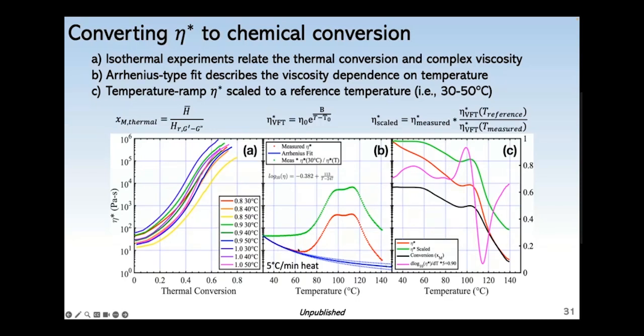And the raw viscosity is red. So afterwards, I scale the complex viscosity, accounting for that temperature change, or how much I would expect the viscosity to change with temperature. And that green line is showing how much it's been scaled to account for that temperature dependence. And then in the last plot, I'm showing some example results where I've taken the measured viscosity, shown in red, and then scaled it to a reference temperature, which is either 30, 40, or 50 C, where I did my isotherm tests. And then I match it to the conversion in the first plot.